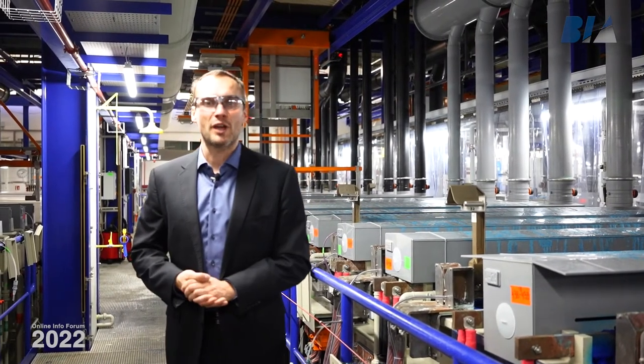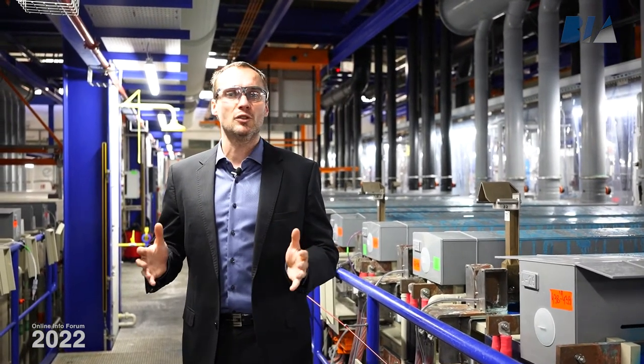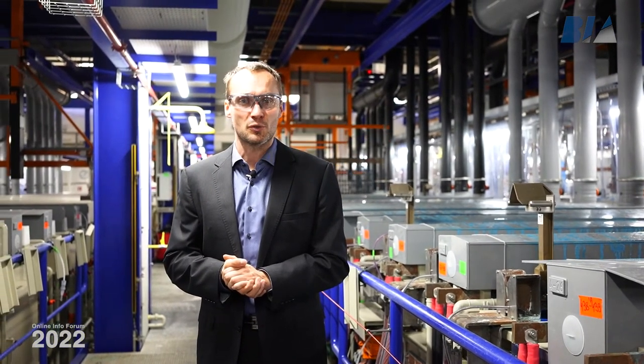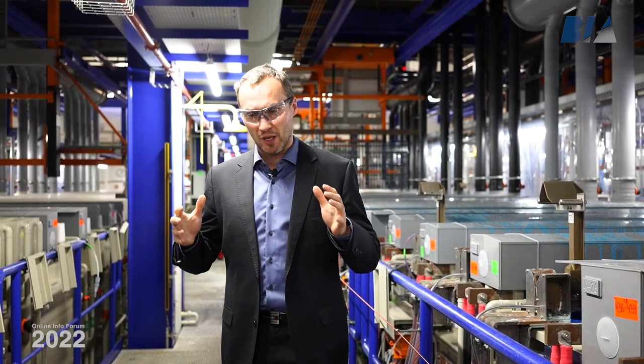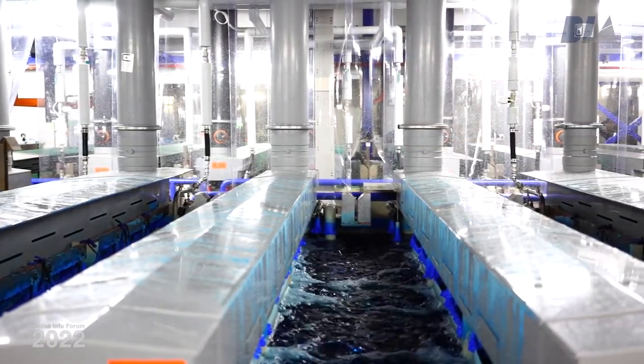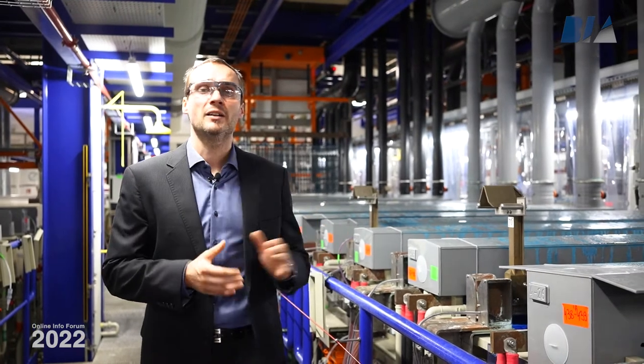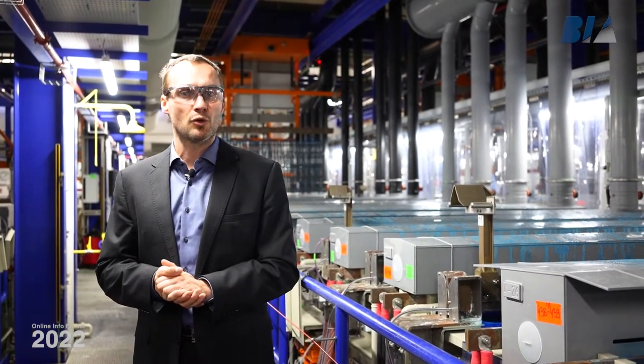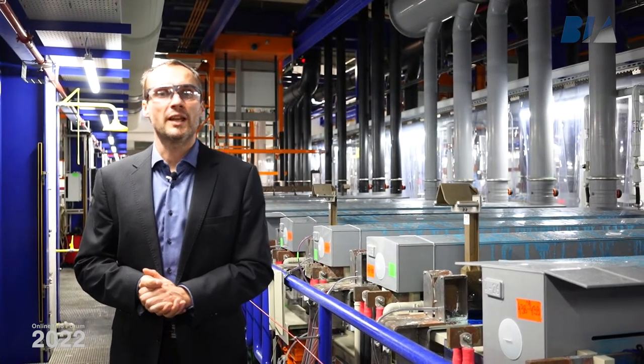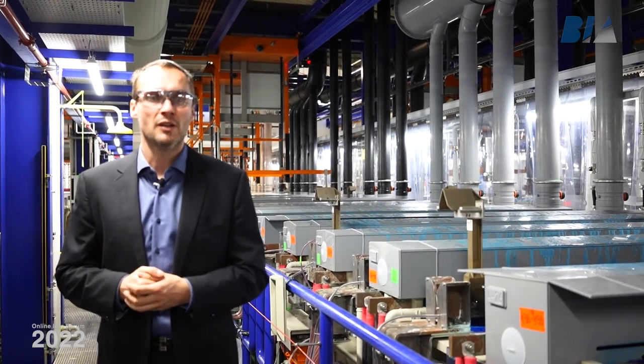Now we are in the middle of our production line, the new so-called BR2 here situated in Solingen. As already mentioned, it is a completely new constructed plating on plastics automotive industry plating line. So we are able to set up interior as well as exterior layer systems and the different nickel technologies to match the different surface appearances of the OEMs. The plating line is directly installed with trivalent chrome systems. We have no layer system containing hexavalent chrome, so we are directly qualifying and implementing the new technologies for the future on the layer system with trivalent chrome as finish.